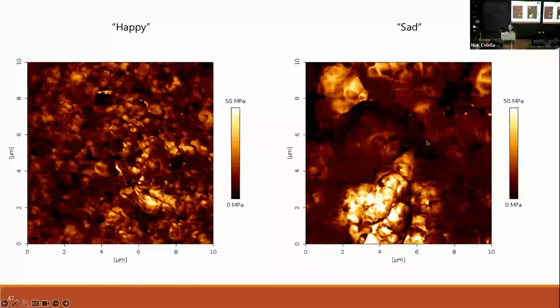The sad ball's what's called styrene butadiene rubber. It's a copolymer. So there's two different functional groups present in terms of the polymer chain, side chains. And one is much stiffer than the other. And that's what allows us to tune our glass transition temperature based on the ratio of those two polymers that are present.